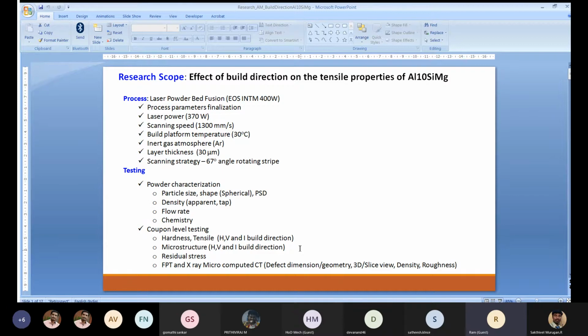What we did in this work is we fabricated the tensile coupons in different build orientations, build directions. Samples are oriented at 0 degree, 45 degree, 90 degree. So 0 degree is nothing but the horizontal plane, 45 degree is the inclined plane, and 90 degree is the vertical plane. Samples parallel to the horizontal direction, perpendicular to the horizontal direction, and inclined at 45 degree to the horizontal direction were built, and we tried to understand how the property varies with respect to the directions, especially the tensile properties.